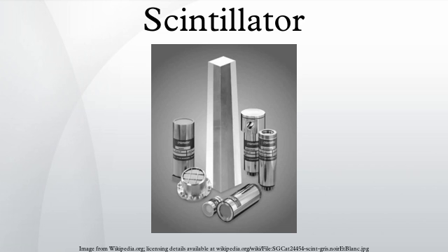Liquid scintillators are easily loaded with other additives such as wavelength shifters to match the spectral sensitivity range of a particular PMT, or 10B to increase the neutron detection efficiency of the scintillation counter itself. For many liquids, dissolved oxygen can act as a quenching agent and lead to reduced light output, hence the necessity to seal the solution in an oxygen-free, airtight enclosure.